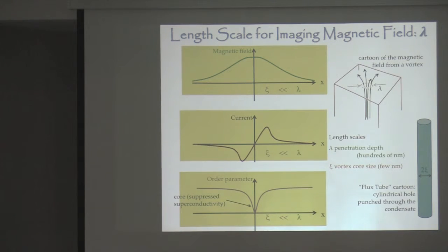Okay. So this is another reminder of the length scales involved. This is really a slide about vortices, but the conclusions are general. There are two length scales: the penetration depth and the coherence length. In the pnictides, these are strongly type 2 materials, like the cuprates. Lambda is hundreds of nanometers. The coherence length, which is approximately the size of the vortex core, is just a few nanometers. We're doing imaging that ultimately comes from magnetic field. So the scale for magnetic fields at the surface of the sample is given by the penetration depth. And that's our ultimate imaging resolution for superconductors.